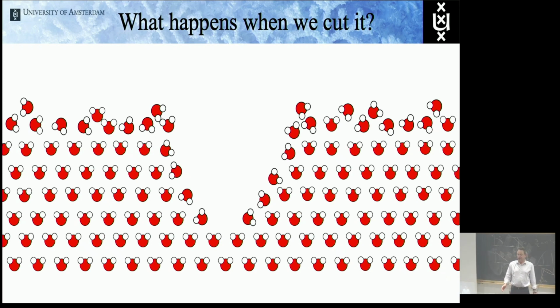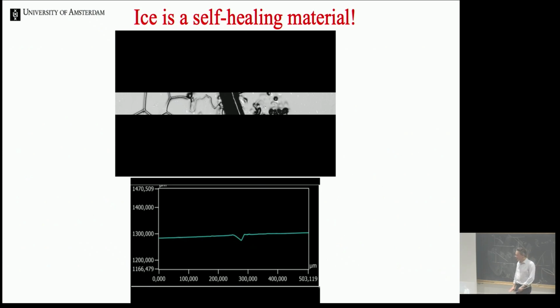So the question is, is ice a self-healing material? And the answer is yes, ice is a self-healing material. This is one of the first observations. And so what you see here is a scratch that we made in the ice. These are grain boundaries, so our ice is not very pretty. But the scratch, we can measure with a profilometer how deep it is. And then we simply leave it with its equilibrium relative humidity.